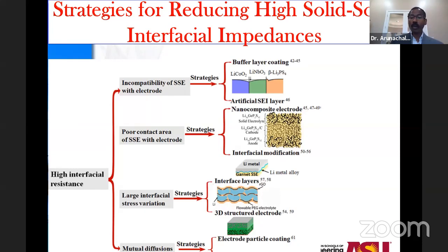And also have particle coatings. So in terms of improving the diffusion or having a longevity of the electrodes, you can have the electrode particles coated with electrolyte, as the electrodes become closer to the electrolyte structure. So again, functional gradation in terms of improving performance and durability. Cost probably is not being looked at very carefully, but as of now it's probably on the higher side because these materials cannot be co-sintered or the process is not available as yet. But again, there are opportunities to integrate all these materials to have extremely high performance with wonderful safety features, along with maybe reduced cost once the batteries are being made in volumes.